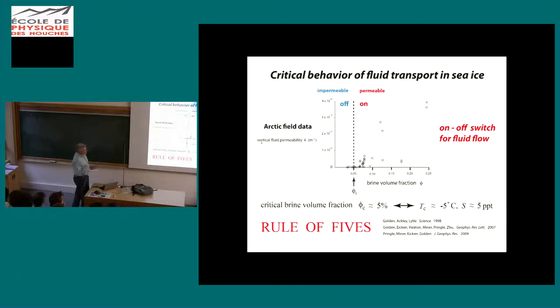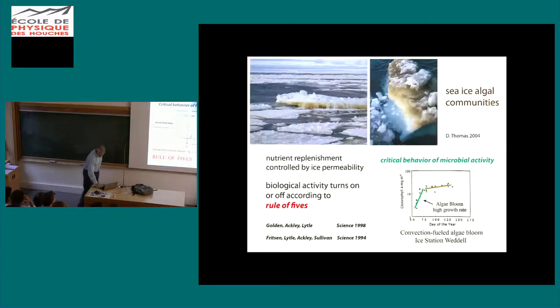By a kind of coincidence, by a certain law called the Frankenstein-Garner relation that gives you the brine volume fraction as a function of temperature and salinity, this critical value of 5% for classic congelation columnar ice. I have to say that because we have another result for so-called granular ice. And this 5% corresponds to a critical temperature of -5 Celsius for a typical bulk salinity of 5 parts per thousand. Hence, it's become known as the rule of fives.